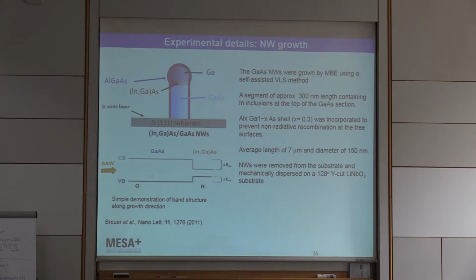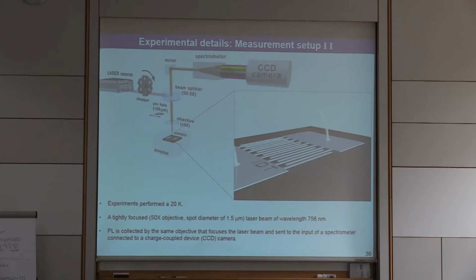These are a few more details on the nanowire. It's grown by this vapor liquid solid method, gallium arsenide, MBE. What is important is that you have this protective AlGaAs shell, which prevents non-radiative recombination, and also this inclusion of this recombination center, this InGaAs structure. And typically the length of the wires is on the order of 7 micron. Okay, so this is the experiment.